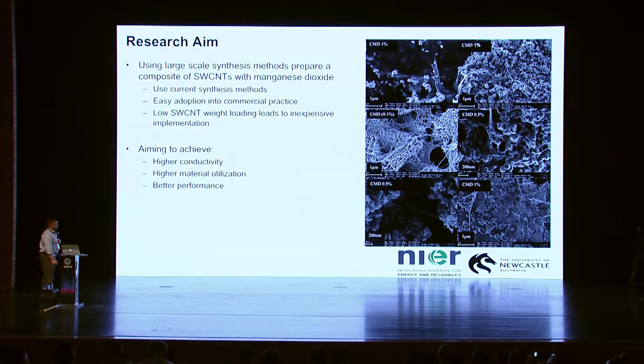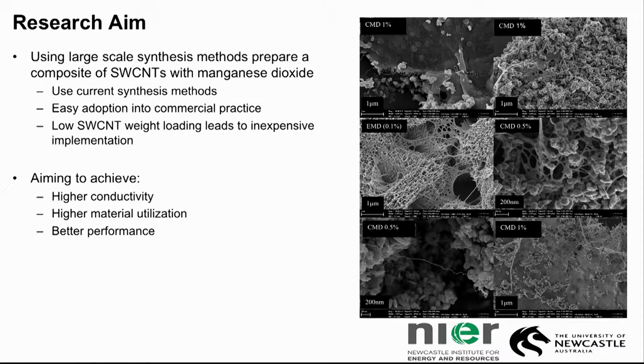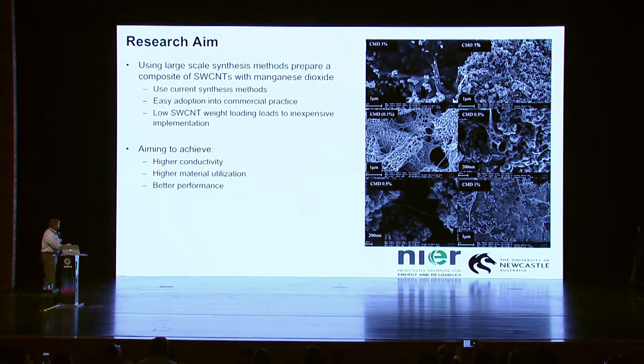Okay. Here's just some examples of the inclusion of carbon nanotubes into our various systems. These are some chemical-based systems, and you can see there evidence for the carbon nanotubes being wholly and solely embedded in amongst the active material in that particular system. We do have some instances here of clustering of the carbon nanotubes, but nonetheless, we still have a very, very intimate mixture of the active material with the carbon nanotubes in these cases. Okay. And so what we're aiming to do is basically achieve higher conductivity within our cathode and hence achieve a higher material utilisation and ultimately get a better performance out of that system.